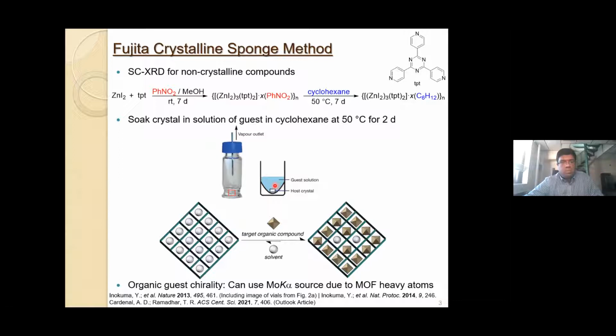target molecule will eventually enter into the crystalline sponge, be able to kick out the solvent, and through a thermodynamic equilibration process, become ordered and stabilized within the host framework. And then you can take this host-guest complex and subject it to X-ray crystallography in order to determine the structure of the target molecule.